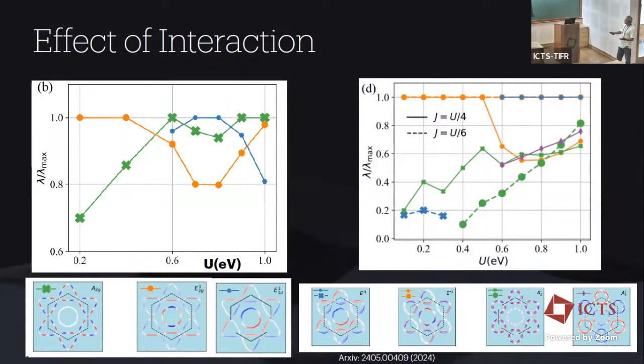If you look at the solutions as a function of U, you find that the solutions do change. Effectively, the symmetry of the solutions does not change significantly. The solutions that I show in this region, without spin-orbit coupling and with spin-orbit coupling, for low U versus high U are primarily the same irreducible representation, but with larger mixing of the odd parity, triplet contribution. It means that as you increase U, the triplet mixing in your superconducting gap grows.